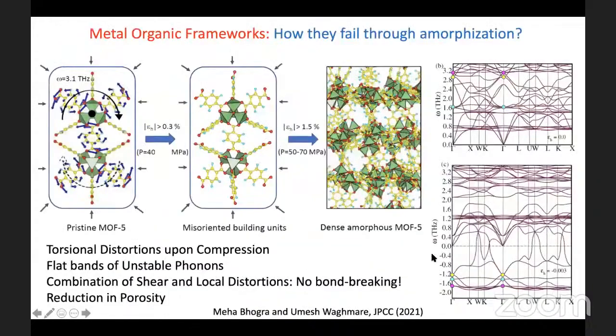Next, Pradeep. So next is an example of a type of molecular material called metal organic framework. These are, of course, a very interesting, rich class of materials, but many people worry about their stability, mechanical as well as over the long term. So they often fail through amorphization. So here we took a very simple example of a classic MOF called MOF-5, and it is known to amorphize at relatively extremely small pressures, like 40 megapascal, the material amorphizes.